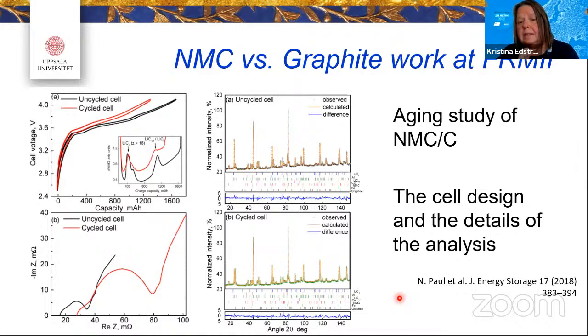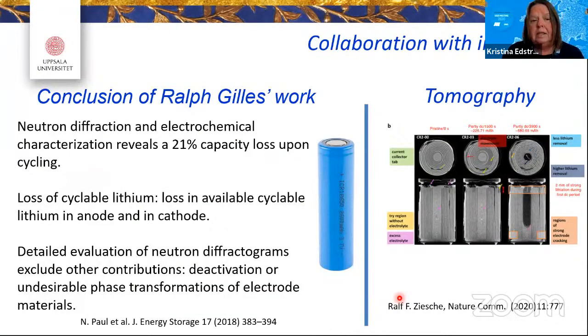And this size also makes this study more trustworthy than when you work in a little small lab cell. So this is really the work of Ralph Gilles and what he's doing. What he could see is that you have a 21% capacity loss upon cycling, and the reason for this loss is a loss of cyclable lithium. And it's both in the graphite and in the NMC cathode. So this detailed evaluation is very important, and this is very useful for industry.